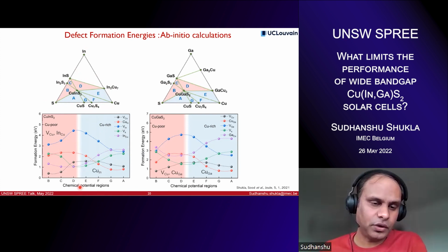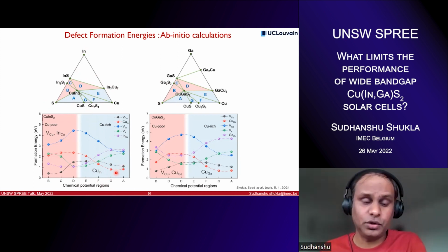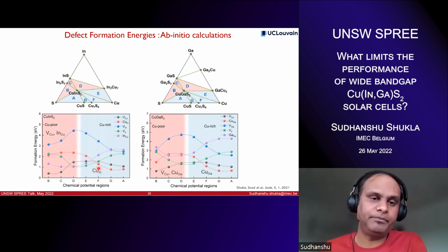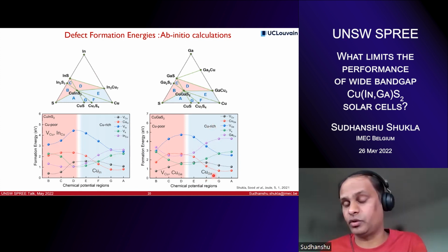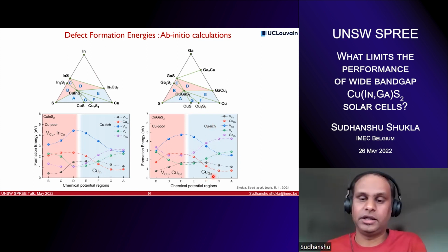As you can see, for the copper-rich regime, you have the copper-over-indium antisite defect that has the lowest formation energy, which is given by this red curve right here. So when you are in the copper-rich domain, this copper-indium defect formation is very highly likely. Same when you go for the CGS, if you are in the copper-rich domain, this antisite copper-over-gallium formation is very highly likely.